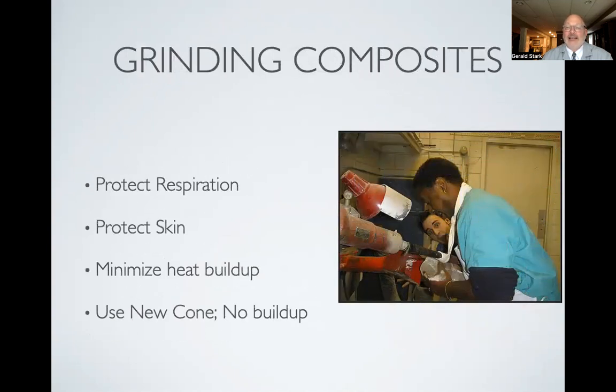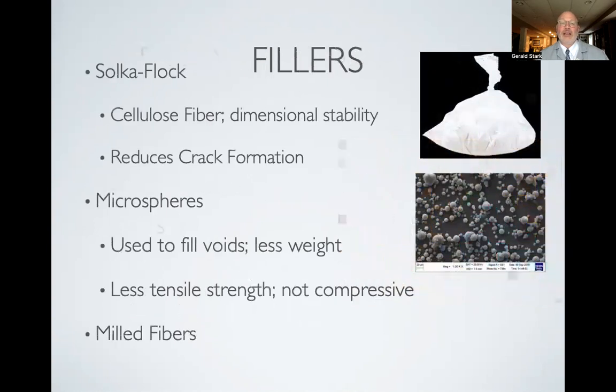When we grind composites, one is to protect yourself. These guys aren't really using any sort of masks, but you need to protect your skin, and maybe you protect your skin by putting a stockinette over your wrists to prevent carbon from working its way into your skin. And another issue is that the composite dust can get into your lungs, and because carbon is really not biodegradable, it just stays there, and it just stays within your mucous membranes if it makes little slivers into the side of your lung tissue. So when you use a cone, it's important to use a very sharp cone, and one that's lubricated with silicone.